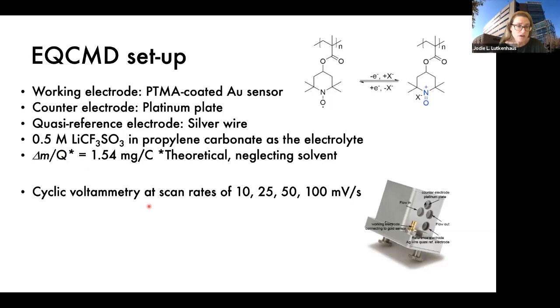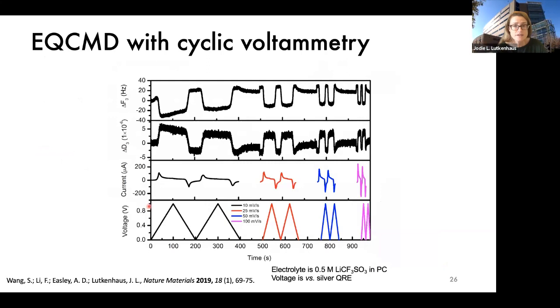You could certainly do other experiments such as galvanostatic charge discharge. This is an example of the raw data that you would get from the eQCMD module. So at the bottom, we have voltage. The input is voltage, so I'm telling the instrument to scan voltage, and the output is current. Conventionally, this is just a cyclic voltammogram that I've unpacked in the time domain. And we're doing different scan rates of 10, 25, 50, and 100 millivolts per second.